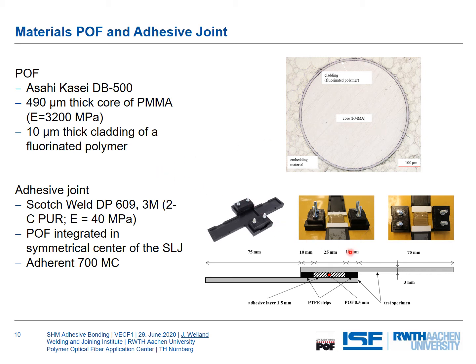We integrated those fibers, as I said, in the classical single lap joint. Down here you can see how we did it. We have a 3D printed device where we can integrate the adherends and also this optical fiber, and then we bonded them with a 2-component polyurethane adhesive. The one thing that is pretty important is the mechanical properties of the fiber and the mechanical properties of the adhesive.